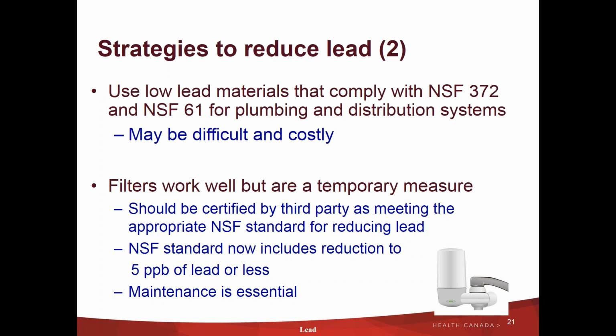Just for those of you who are not aware, the NSF standard now includes a reduction to 5 micrograms per liter of lead or less in the standard. So we were able to get that as a committee change to mirror things going on both in Canada and in the EU. They're driving it towards the lower levels, and also with respect to some of the other issues happening in the US, people wanted filters that would reduce the lead levels lower. And the key messaging, of course, is that maintenance of these filters is essential.